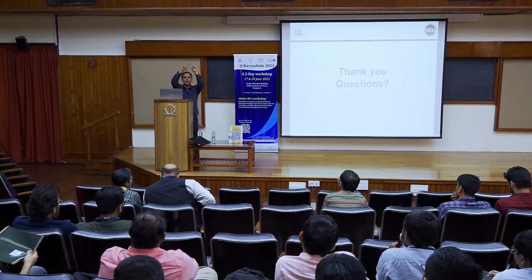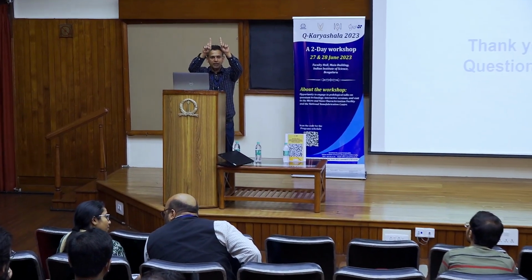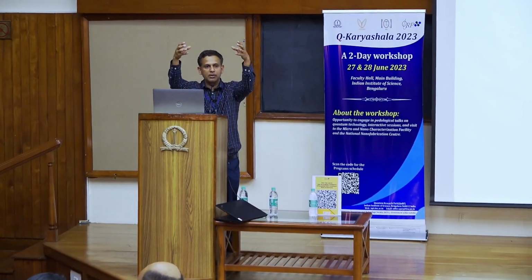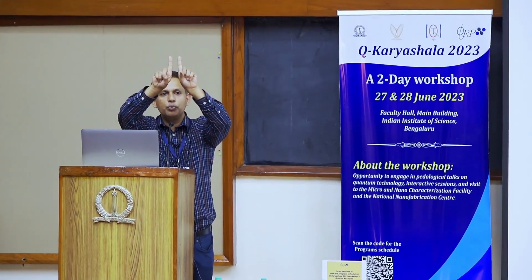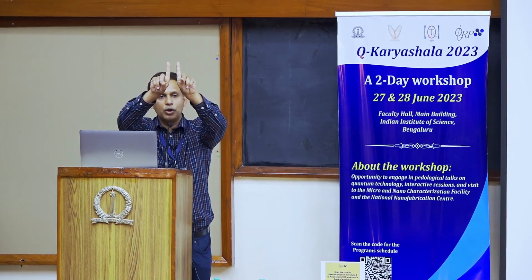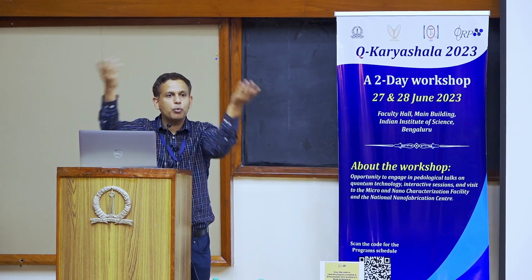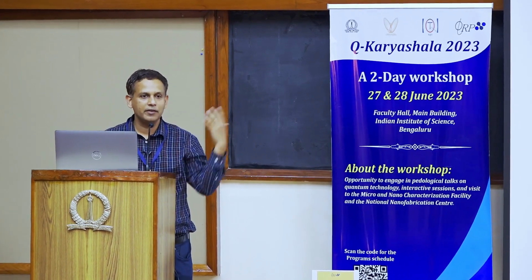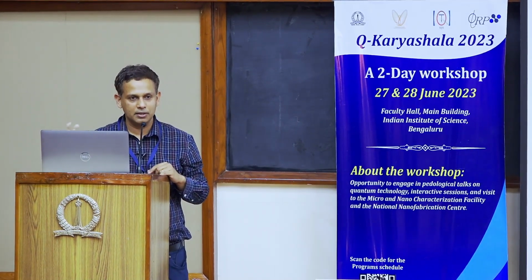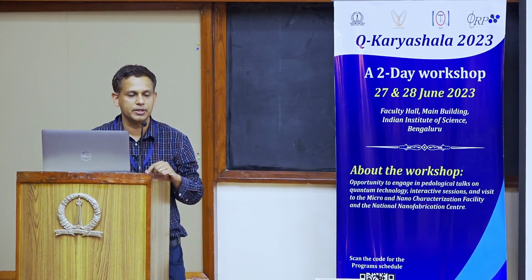Now, if I have a nanoscale magnet here, there are two ways of doing it. If I want to keep track of every spin, then it's not a continuum picture. But when you have a big enough magnet like 10 nanometers, 100 nanometers, you really don't put S_i dot S_j as exchange coupling. What you do is you penalize it with a del square M term. And at that point, it becomes an FEM simulation. So you can use your knowledge of finite difference or finite element to look at these systems. And just like in CFD, you have packages here also. There are people who have done the work, and then you can write scripts to be able to do those simulations.